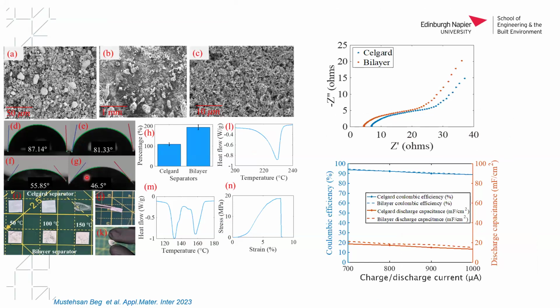So in electrolyte interaction, the contact angle, meaning how the electrolyte is distributing, is the most important parameter to enhance the electrochemically active surface area and also the specific capacitance. We found that the bilayer separator absorbs more water content than the Celgard-based separator. Here you can see some SEM images of this material. I'm not going into a detailed explanation of that. Here you can see that the water uptake of the bilayer is much higher, and it also has very high wettability.